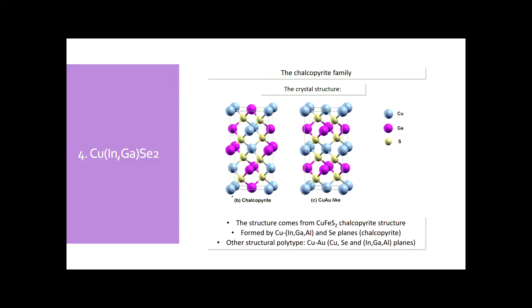So, this is the crystal structure of CIGS. It comes from the chalcopyrite family, where you have copper and gallium or copper and indium planes, separated by the chalcogen plane, either sulfur or selenium, and the same again. But you can have different polytypes, different structures, like the copper gold here. In this case, gallium and copper are sharing the same planes. In this other case, copper is in one plane, then the chalcogen, then gallium, then the chalcogen, then copper. Okay, and these two materials can have very different properties, even just from exchanging the atoms.